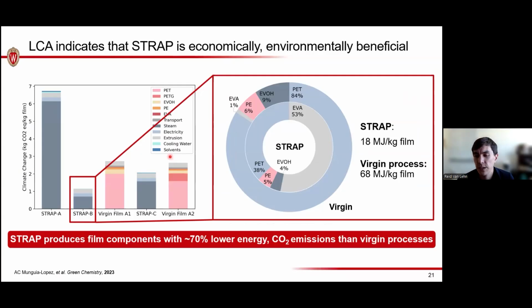Yeah, of course. So actually, this nicely ties to what the last question was. I didn't talk about this. STRAP A is where we add an anti-solvent to introduce precipitation. So this means that I have both a good and a poor solvent to remove every polymer. As a result, I get this massive increase in energy usage because I have to separate the two solvents from each other. This is exactly what I mentioned in the last question. So this was a killer for us. Originally we got really high yields because of the anti-solvent. The LCA said that that's a no-go.